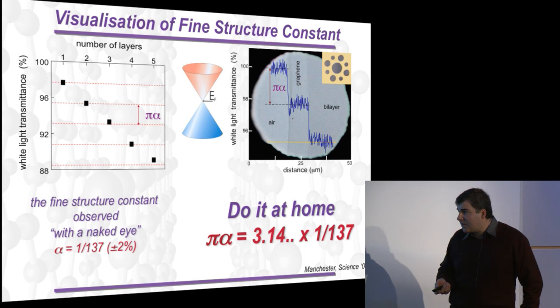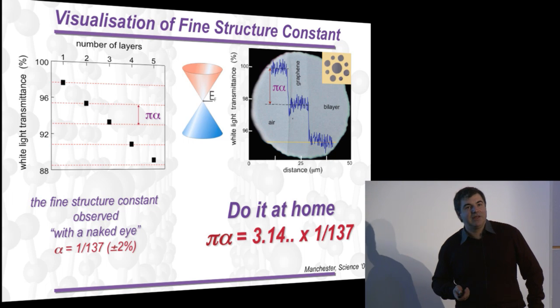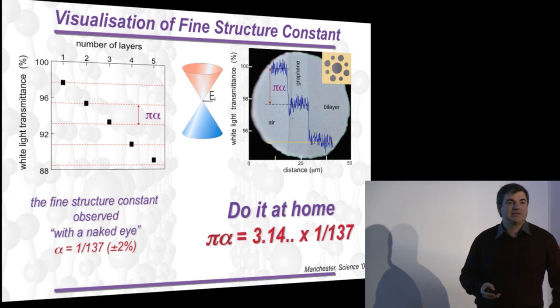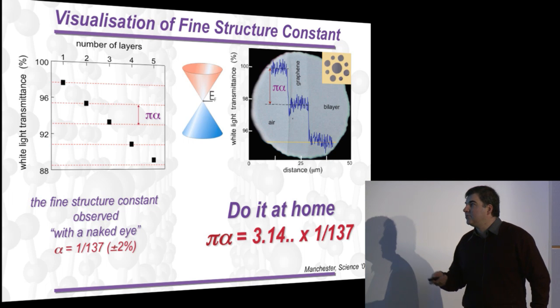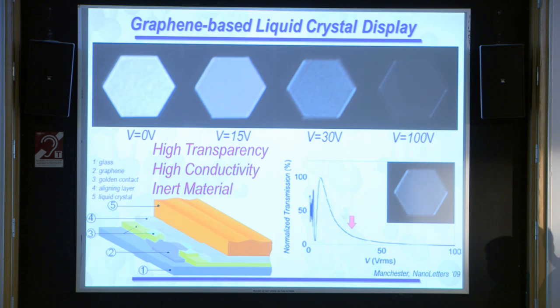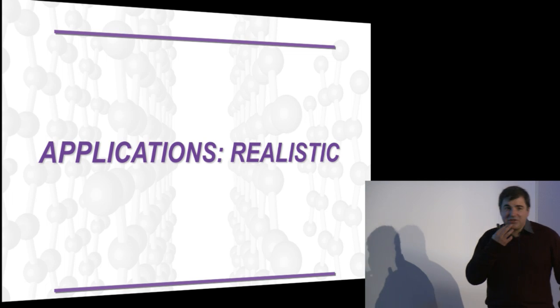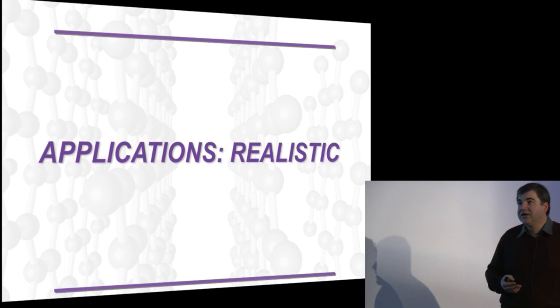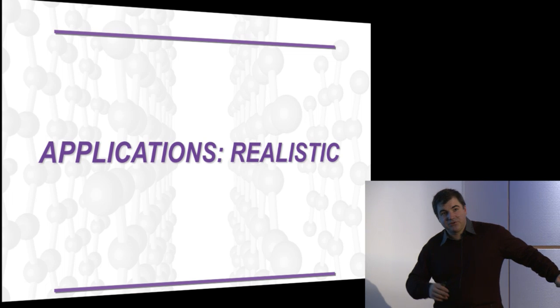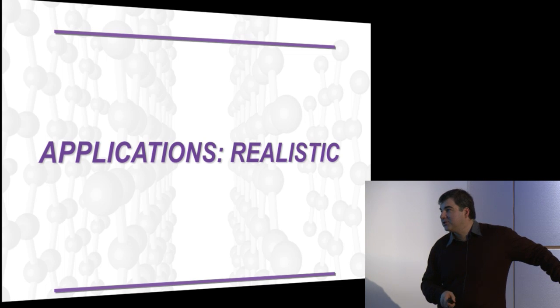And here we created an LCD, well, one pixel of an LCD display, where graphene has been used as a transparent conductive coating to replace ITO, and it does work. You can pinch off the optical transmission quite easily, and here we benefit from its high transparency, high conductivity, but also from the fact that it's an inert and flexible material, so it can be used for future devices. And this basically brings us to the applications, which in principle are quite realistic, but before promising you some future applications, let me show you what graphene has done for us already.